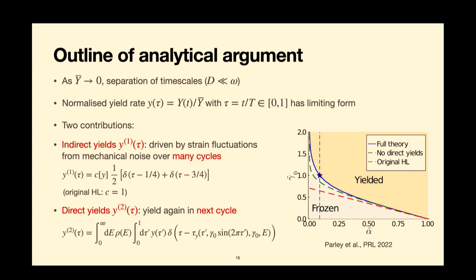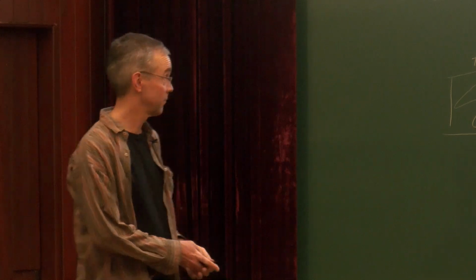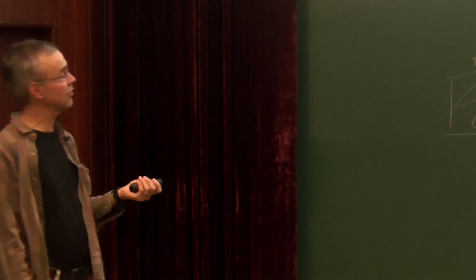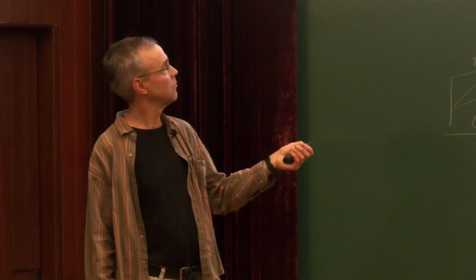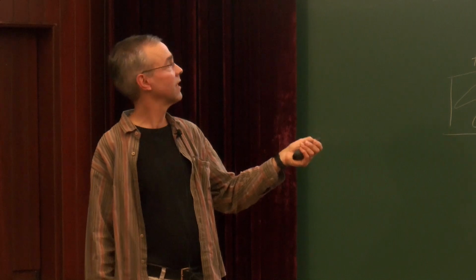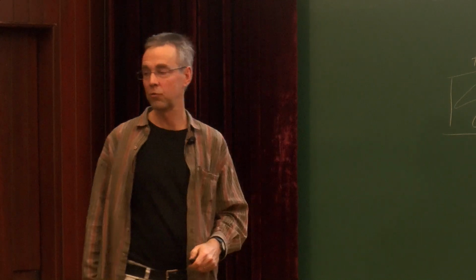One can also simplify the theory and only account for these indirect yields. That gives us slightly lower estimate for this amplitude. What's interesting also is the comparison with the original model, which only had a single yield energy. There, this dynamical transition is actually very simple, and it's a straight line, because it just tells you if your amplitude is lower than your yield energy, then you never yield. If it's higher, then you always yield. That's why in this case it's a straight line. And so it turns out that the fact that we have structural disorder always makes the system more likely to end up in a frozen state and less likely to end up in a yielded or fluidized state.